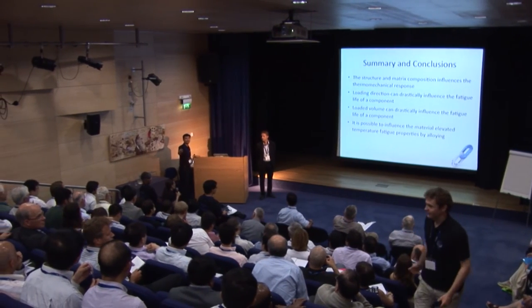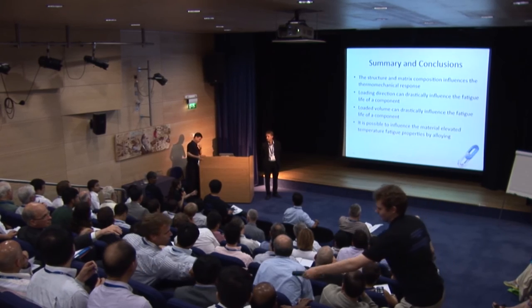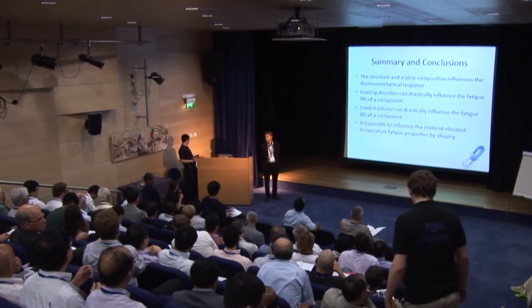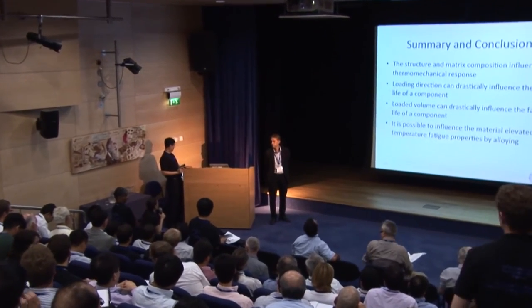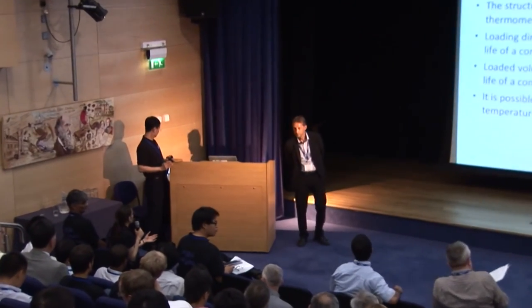I just wanted to know, you said that the austenite in the contact fatigue decayed due to stress and temperature. Is it decaying into ferrite and carbides, I presume, rather than transforming to martensite? That's what we assume when we look into the microstructure. We didn't see anything like virgin martensite. Okay, so it's literally just decomposing. But it's a long time, so it had transformed and then it continued to do something.